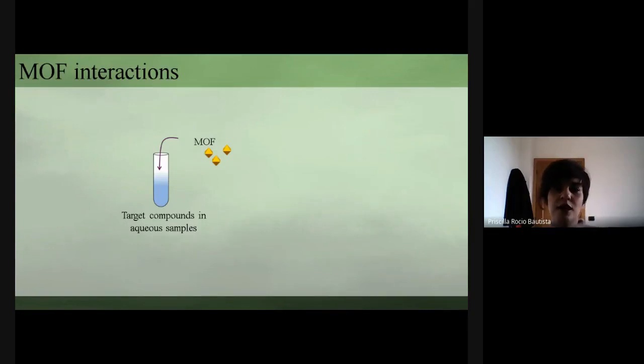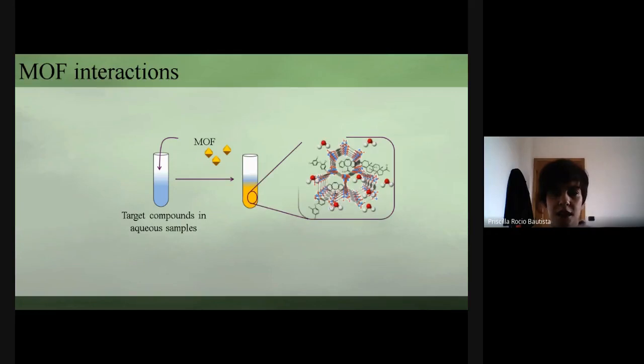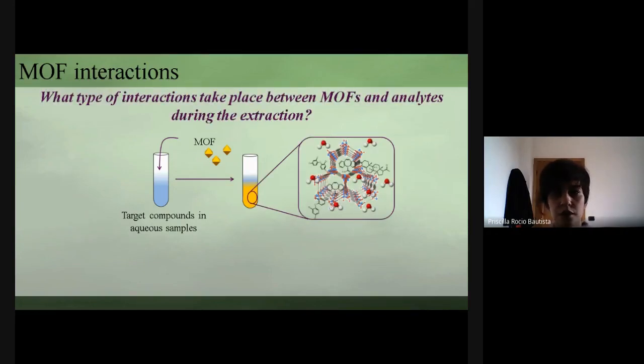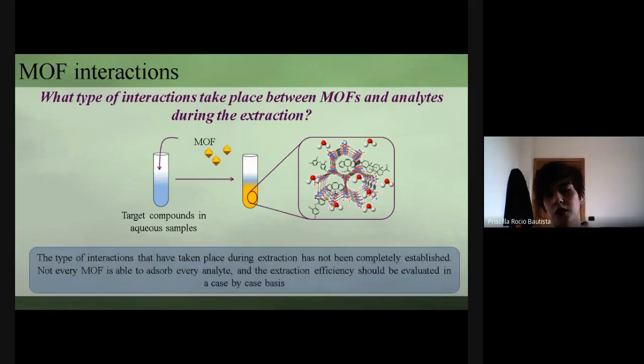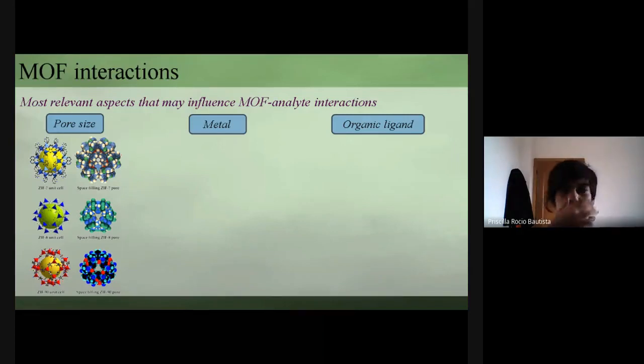Despite the increasing number of studies with MOFs as sorbents in different extraction techniques, few authors have paid attention to study the nature of the interaction between the extracting MOF and the contaminants. What type of interaction takes place between MOFs and analytes during the extraction? The straightforward conclusion is that not every MOF is able to adsorb every analyte, and the extraction efficiency should be evaluated on a case-by-case basis. Regarding the most relevant interactions, the pore of the MOF in terms of size and shape clearly influences the absorption or adsorption during the extraction. But the interaction also depends on the nature of the metal and the ligand.